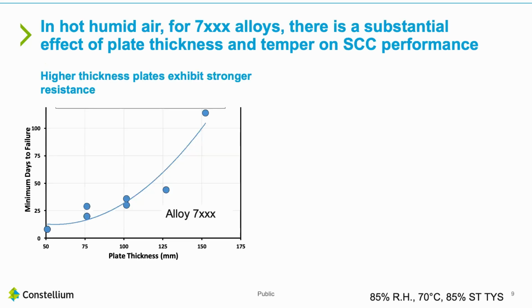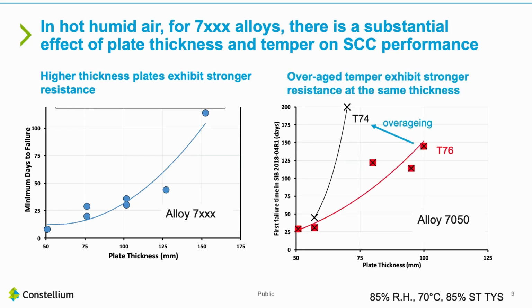So, to go further, in hot humid air there is a strong effect of plate thickness on the 7,000 alloys. The lower the plate thickness, the lower the stress corrosion resistance, which can be attributed to change in grain size and also quench properties. When you overage the metal, you also have a big increase of corrosion resistance. 7,000 series are overaged, but when you go from T76 to T74 temper, you increase the aging duration, and that is beneficial to increase the resistance to stress corrosion.